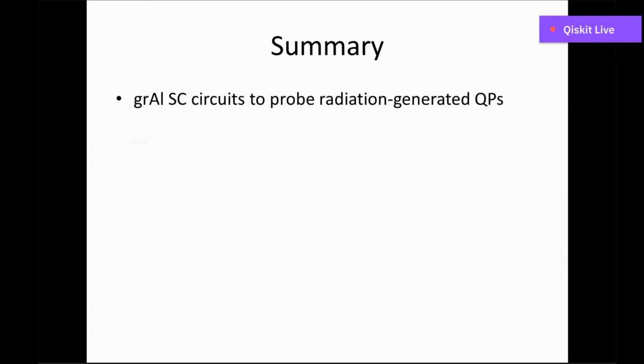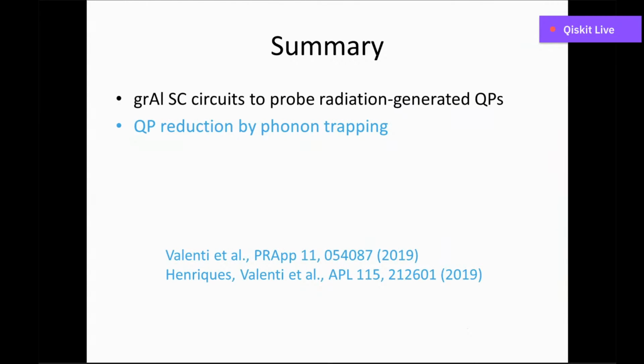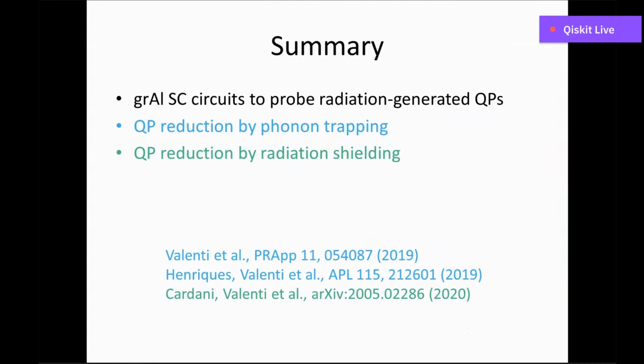Which brings me to my conclusions. What I've shown in this talk is how we used granular aluminum superconducting circuits to probe quasiparticles, and we were interested in radiation-generated quasiparticles. We can reduce the quasiparticle density by employing phonon trapping to get rid of the phonons generated in the substrate. And as a complementary approach, we can reduce the quasiparticle density also by shielding from radiation that would generate those phonons in the first place.